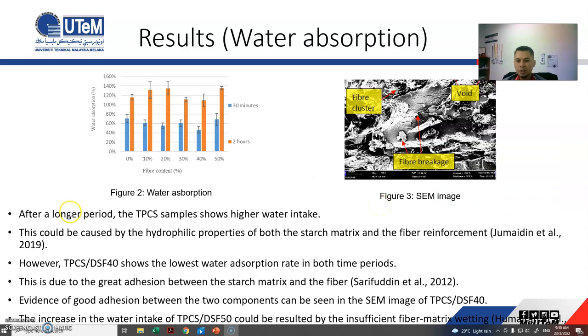In terms of water absorption, this is the result. The blue one is for 30 minutes of immersion, and the orange is for 2 hours of immersion. We cannot conduct immersion for a longer time because the sample started to disintegrate, which is a good finding, because this material will certainly be environmentally friendly when it can be disposed of in water. After a longer period, TPCS shows higher water intake, of course. This could be caused by the hydrophilic properties of both the starch matrix and the fiber reinforcement. However, TPCS/DSF40 shows the lowest water absorption in both time periods.